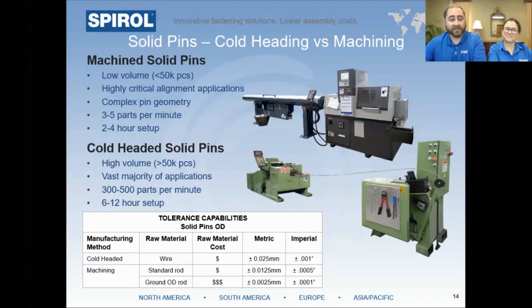Now, with machining, the setup times are typically 2 to 4 hours, and you can produce parts at about 3 to 5 parts per minute. Machining produces slightly tighter tolerances on the diameter tolerance compared to cold heading. Now, with cold heading, you're using dies to deform material into the desired geometry. This is actually exactly how screws and bolts are made, but it can also be used for solid pins.